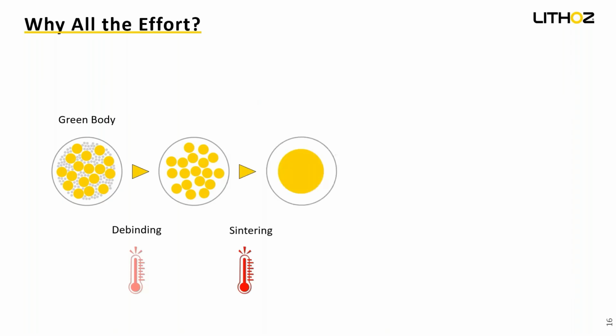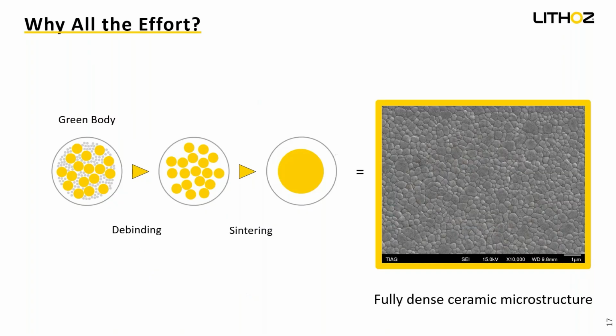As the temperature increases, the ceramic particles bond and the structure becomes dense. This is what transforms the printed shape into a true high-performance ceramic part. The second image shows the result we aim for, a fully dense microstructure with no pores and no defects. Achieving this density is essential because it gives the final component its strength, reliability, and high-performance material properties.